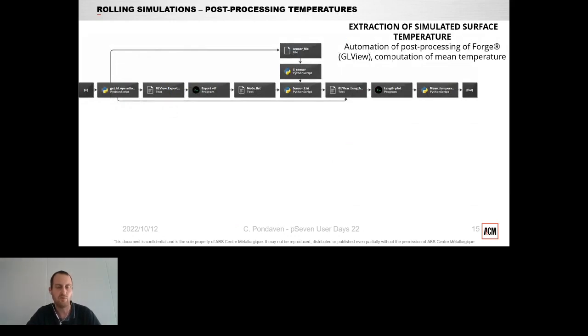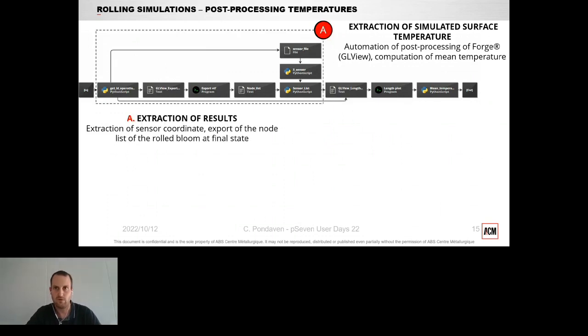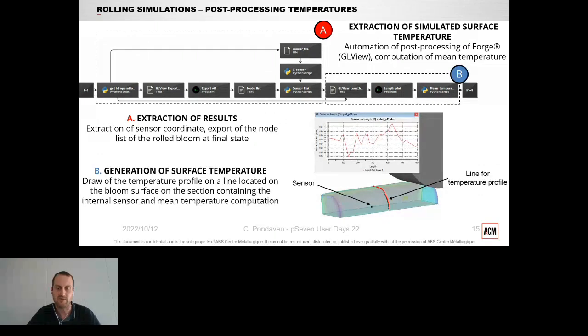Concerning the surface temperature, we have automated the execution of the software used to post-process the results of Forge. First we extract all the nodes of the part after the rolling. We extract also the coordinates of a sensor that is located in the steady state area of the bloom, where we want to compute the surface temperature, and then all this information and implemented scripts are executed in the post-processor of Forge to compute the temperature on the surface of the bloom, and then compute its mean and compare it to the measured mean during the rolling operations.